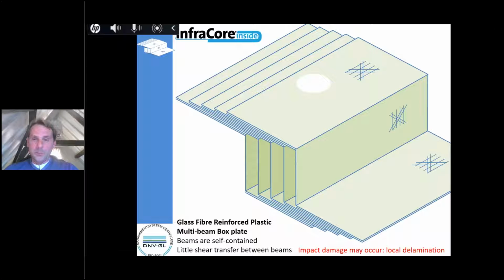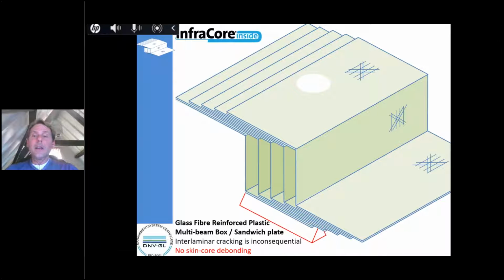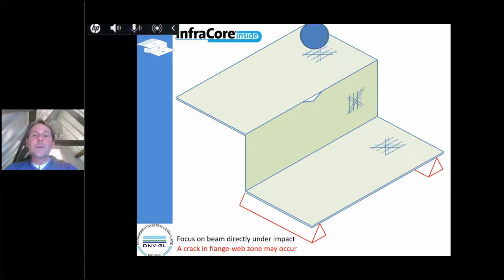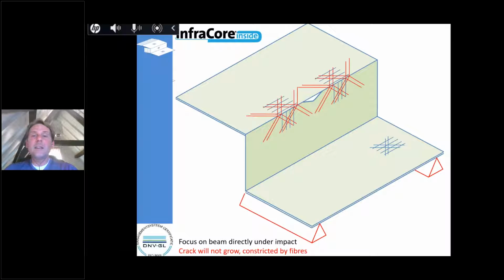And once the product is consolidated, so it has been injected with resin, and you would impact it as I just did, and you would then fatigue it. This is just showing how a fatigue cycle would look like by driving over it with a wheel, but it could be hogging and sagging because of a ship. This local damage cannot grow any further than the overlap that you see in each preform. So again, you see this local impact attacking this vertical web, but there's plenty of remaining material around it, surrounding it, to transfer the loads.